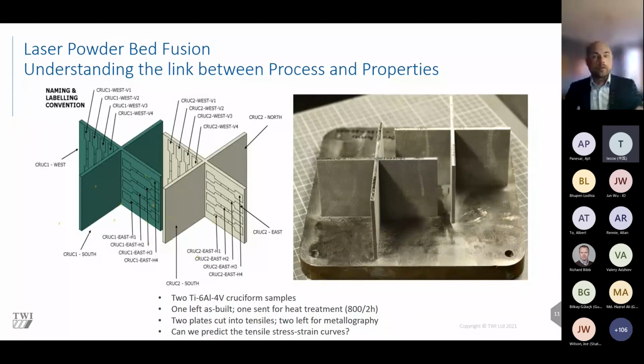Link all of these hierarchies together, dial into regions, do some fancy calculations, dial out, get macro scale residual stresses, and then we can put it to the test. So in this case, we built some cruciforms out of Ti64. One was in the as-built condition, the green, and then one we gave a conventional heat treatment at about 800 degrees for 2 hours. We then cut out vertical and horizontal tensile tests to see how well we can estimate and predict how these parts are going to behave.